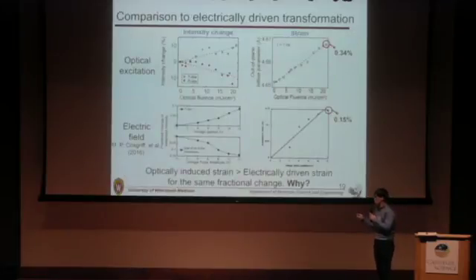And to systematically study, we have measured the intensity changes as a function of fluence and also lattice parameter, and compared with the electrically driven phase transitions. And what we have seen is the T-like phase intensity goes up and R-like reflection intensity goes down, which means the fraction of the T-like phase increases and the fraction of the R-like phase decreases. So it is evidence that the R-like phase is transitioned to the T-like phase, and we also see the linear expansion with increasing optical fluence.